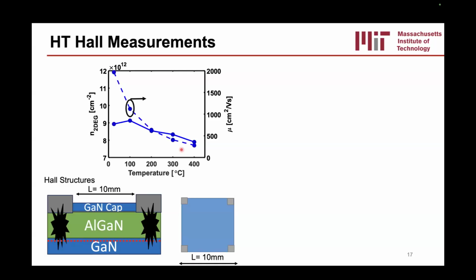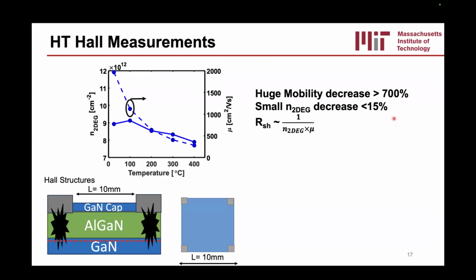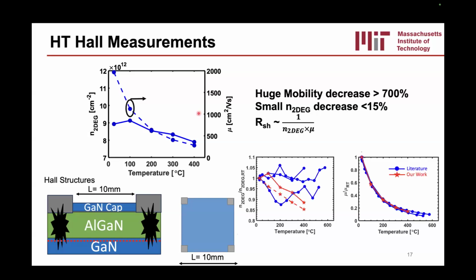On the other hand, if we look at the mobility, which is this dashed line here, it goes from about 2000 to about 250. And so that's a 7x reduction. So the mobility decreases by 7 times, or 700%, while the 2DEG density decreases by about 15%. And the sheet resistance is inversely proportional to the product of these two. And so we can safely say that the large sheet resistance we see is due to the mobility degradation.